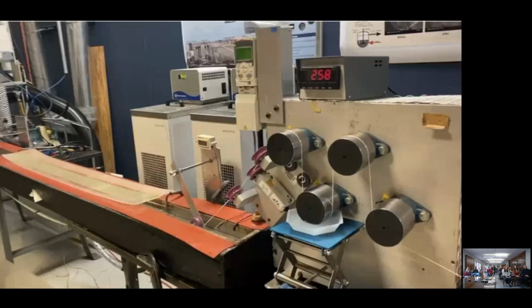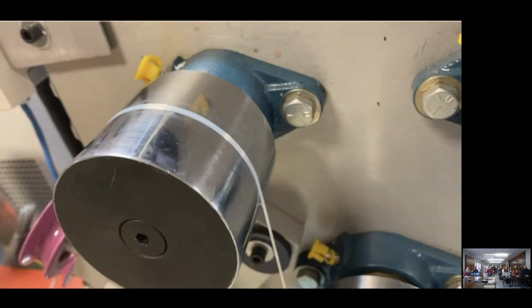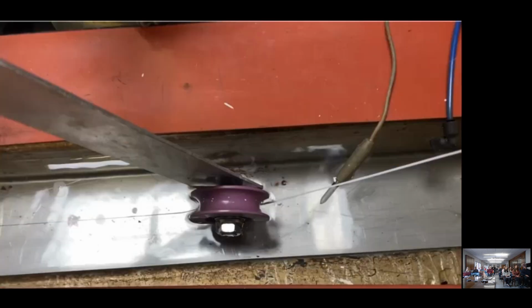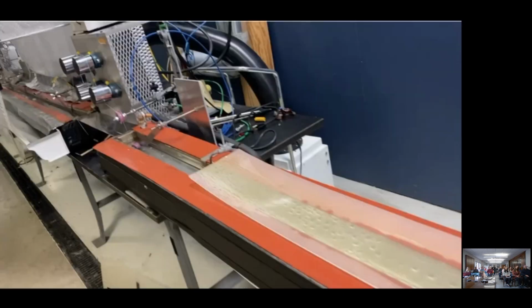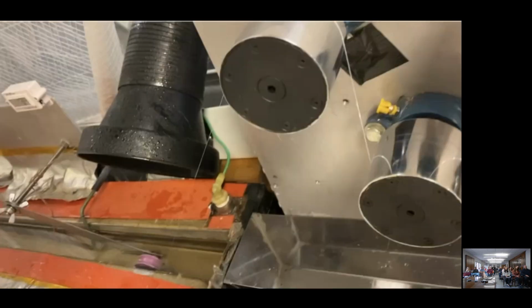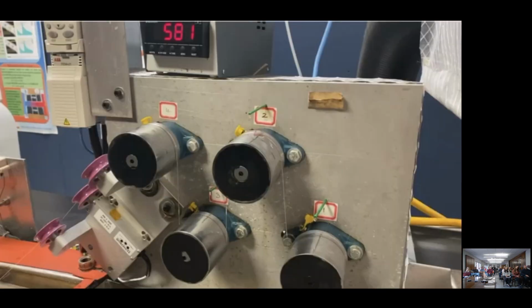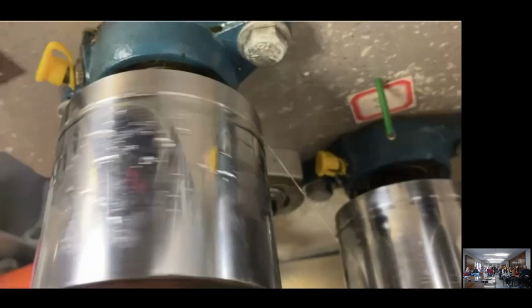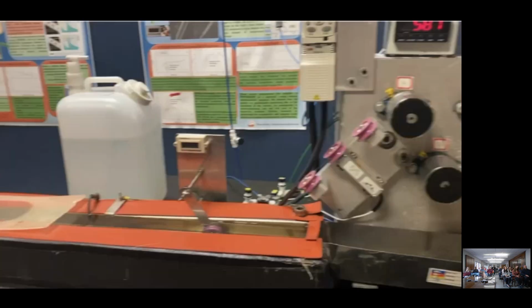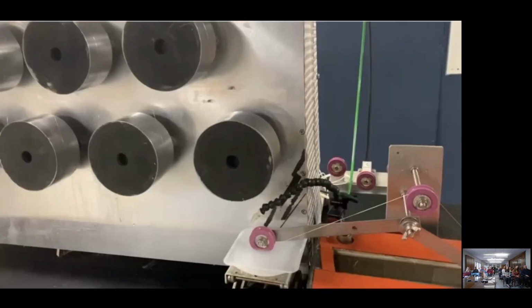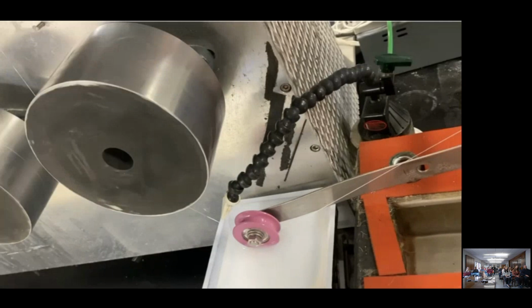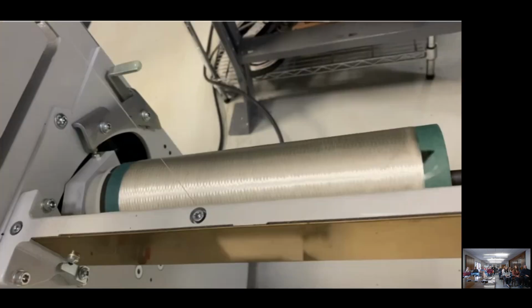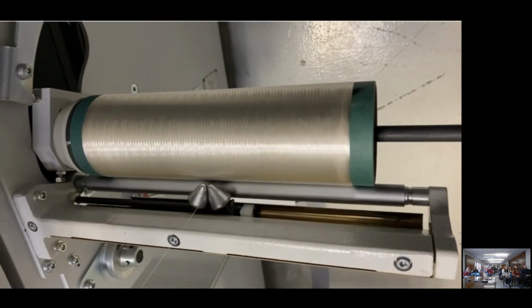This is going to go kind of fast here. The fibers are drawn through hot water, accelerating and attenuating the filaments. They're dried, and then the dry filaments go into hot glycerol above the glass transition temperature. They're drawn again, and you can see the filament's smaller, maybe a little more lustrous. That filament goes through hot water to wash off any excess glycerol. We apply a spin finish, dry that, and then the filament is taken up. It's a really fast video, everybody, but that's essentially how industry produces pan-based carbon fiber.